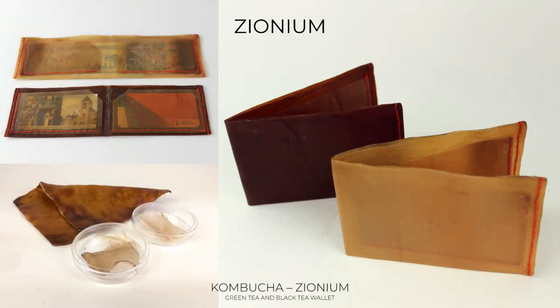Of course, when you stitch it with a sewing machine, what happens is that you perforate the kombucha. That means that water and humidity can actually penetrate really well. And it will start swelling again. So it might not be the ideal solution, but we're getting closer to it.